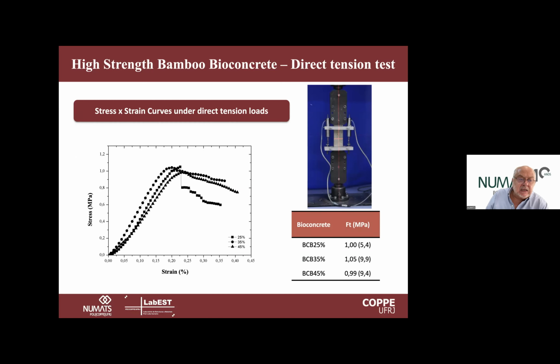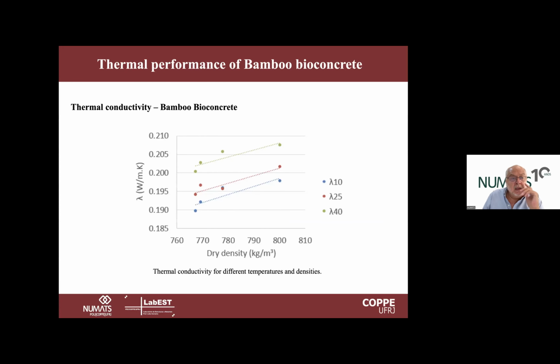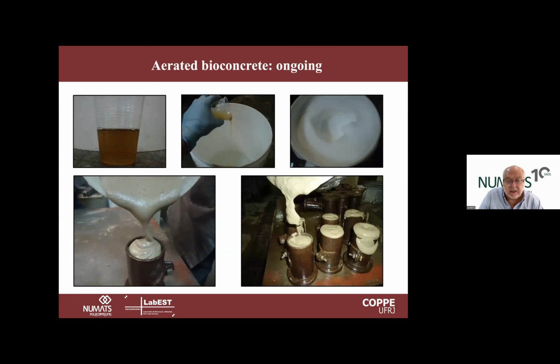So the tensile strength can be in the range of 1 MPa, and under indirect loads, it can go up to 1.5 MPa. A very interesting property of this material is that we can have a low density material. You see the density here can be as low as 750 kilograms per cubic meter, and then the thermal conductivity is quite low, which can be good also for the thermal efficiency of buildings using these materials.